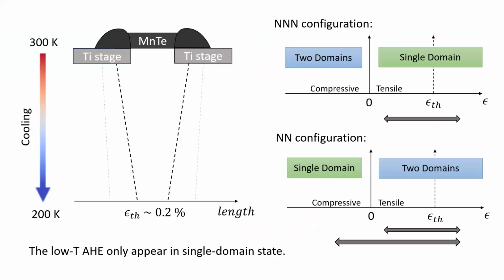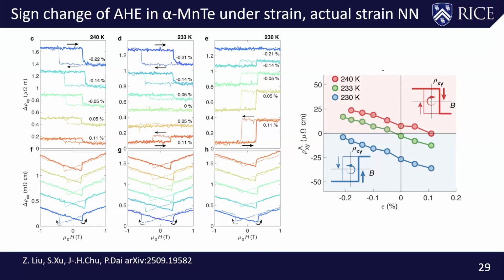And what's even more interesting is the additional detail that the sample, when it's mounted on a titanium stage and cooled down, intrinsically has some temperature dependence, and we're taking into account all of this effect. So what's even more interesting is that if you look at the anomalous Hall effect as a function of temperature, you can see at high temperatures it's behaving in one way, but in the temperature regime roughly around 230 to roughly 240 Kelvin, this hysteresis loop actually changes sign. For example, in this case, the loop goes clockwise.